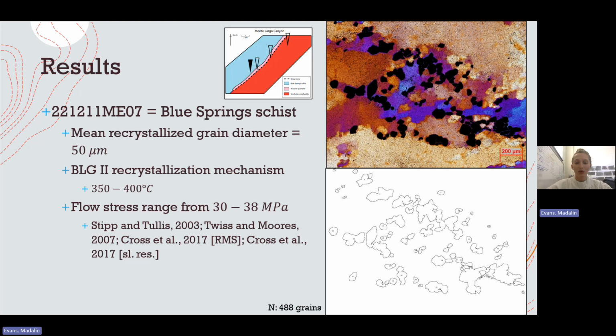And before I go on to the paleostress, I want to describe these images first. So up here, we have got an image in the XZ or the kinematic plane through the polarized light microscope, in which the gypsum plate has been introduced. And as these images are being processed and being manually measured, I had outlined them and filled them in with a black color, so that way I wouldn't keep remeasuring the same grain over and over again. And one of the benefits that was supposed to come from that is that it would produce this outline for me of each individual grain and essentially count each of the grains for me.